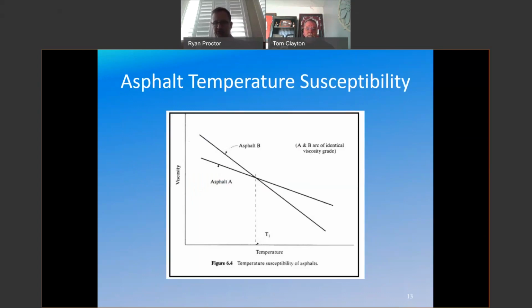This is an old asphalt slide. I took this from Marshall Shackelford. This is from the 50s, actually. And it shows again that if you're looking at T1, so the bottom part of that graph is temperature. And if you will, those lines are the performance of an asphalt. So it's simplified, right? And if you look at both of those asphalts at T1 at the temperature, whether it's penetration or viscosity, they could look the same. But if you look at them in the road, or if you looked at them in the lab under different conditions, they have very different performance. And this slide really focuses on how temperature susceptible different asphalts are.